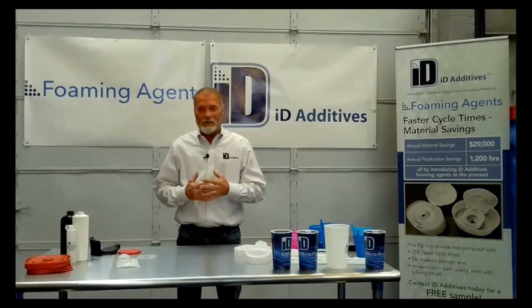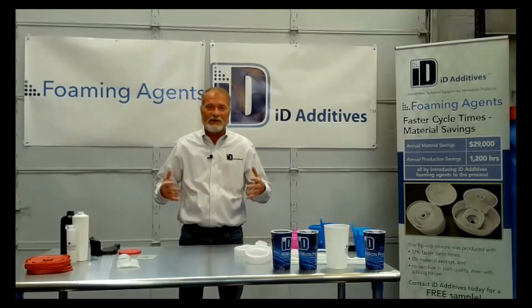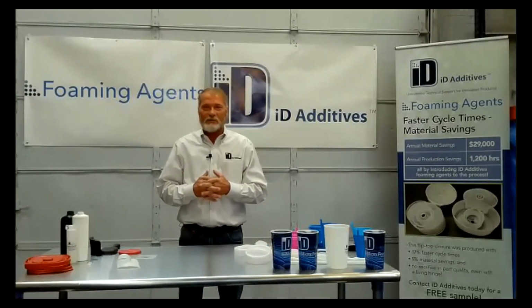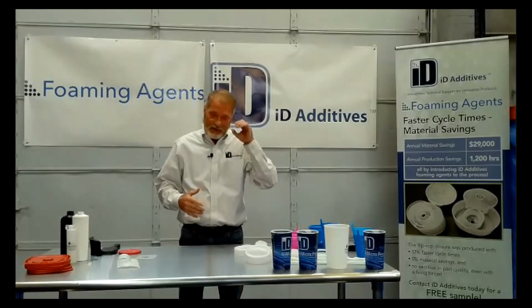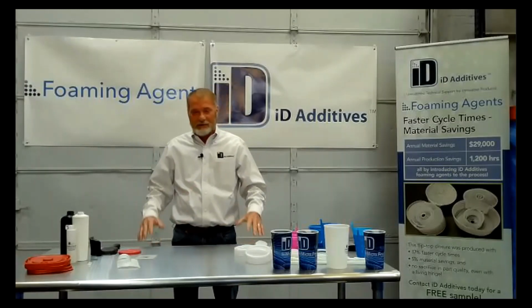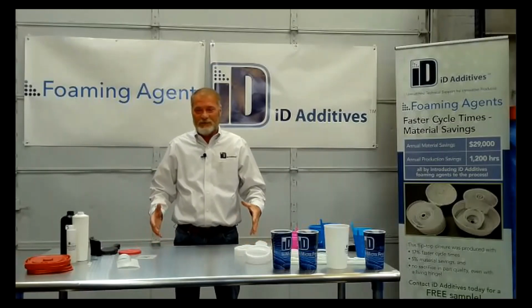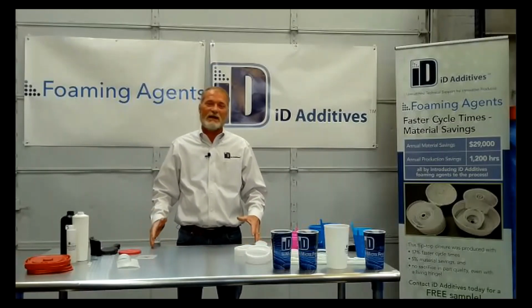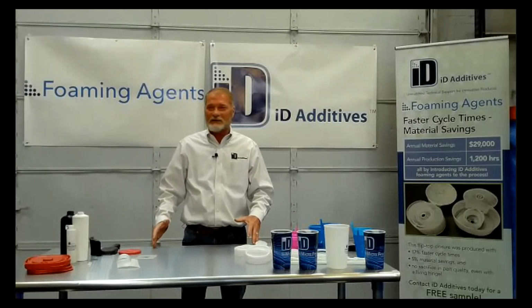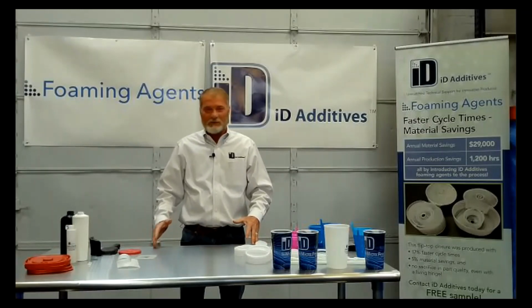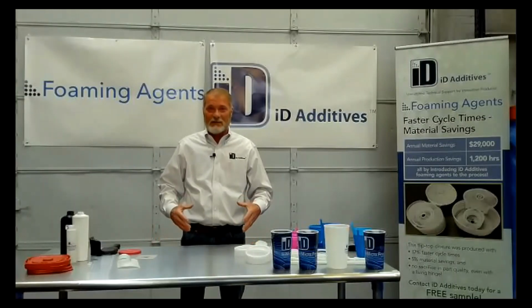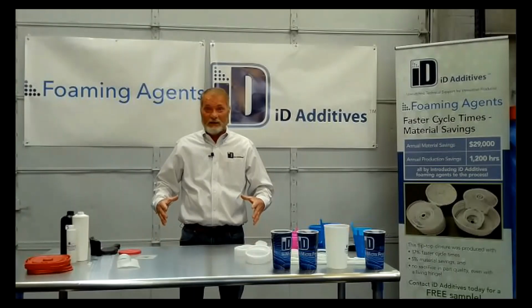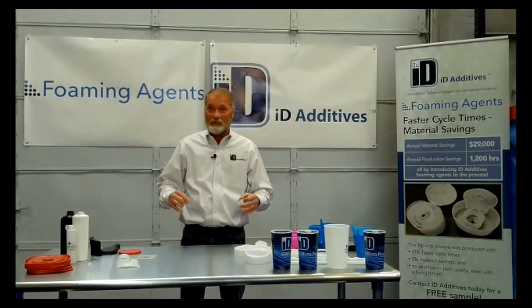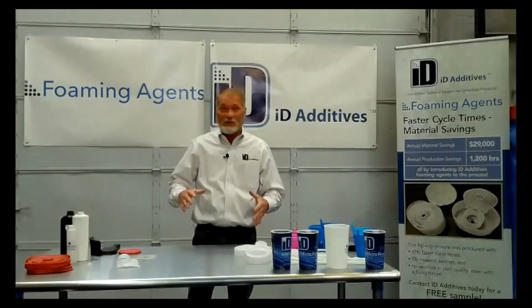So when I foam, let's say a 30% or 40% glass, and I take 4% weight out of it, they kind of scratch their head and say, this part is 4% lighter, that's probably not enough. But you have to understand that if it's a 30% glass or talc or calcium, 30% of that part I can't foam. So when you're pulling 4% density out of the whole part, the material that costs the most, that's your polycarb or nylon or polypropylene, that's what I'm reducing.